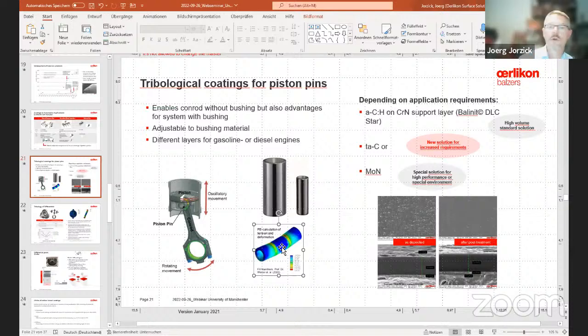And if you would not support it underneath, and we saw that in the very beginning when we had a simple coating architecture without this ductile interlayer, you will have cracks in the DLC coating, and then the DLC coating will also start to peel off. And that is exactly the reason why this coating architecture was adapted, in order to help the component survive, or the coating survive.